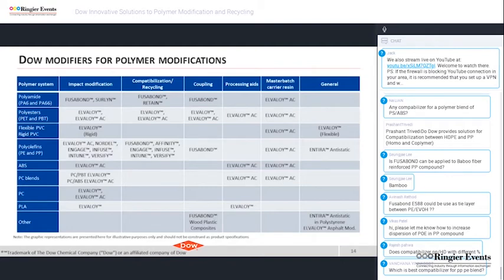At the same time, Fusabond M603 enables multi-layer film to be used for injection molding application with better notched Izod impact strength than traditional grafted compatibilizer in HDPE EVOH blend. Another function of Dow polymer modifier is used as coupling agent to provide a chemical hook in a few polymer system, and it enhances the adhesion between filler material and the polymer matrix. As I shared in my previous slide, Fusabond M603 functional polymer helps to improve stiffness, flex strength, and reduce water absorption of wood plastic composite when compared to traditional grafted coupling agent.